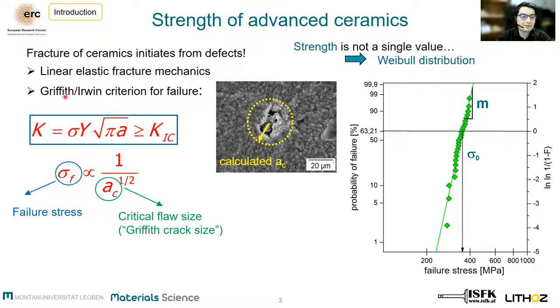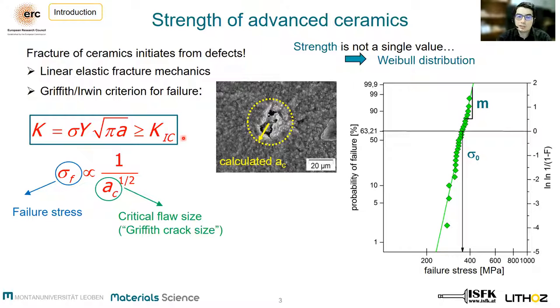If the stress intensity factor K at crack tip exceeds the fracture toughness K1c of a material, failure will occur. Since these defects differ in size, shape and location, ceramics cannot be described with one single value. Therefore, we need to do statistical analysis of Weibull diagrams.